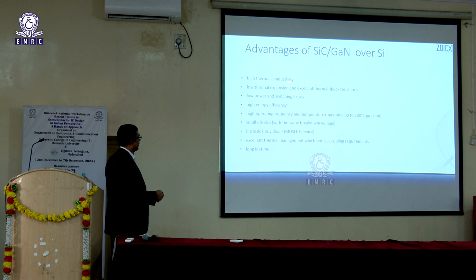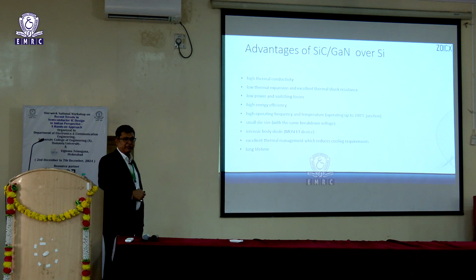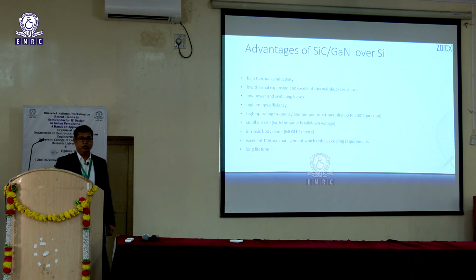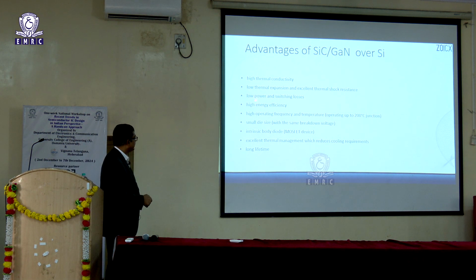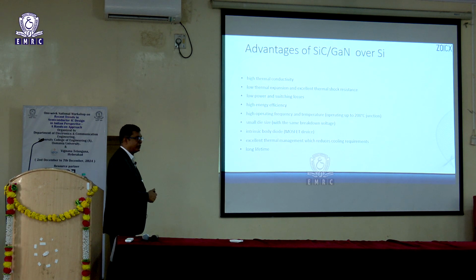I told you about the high thermal conductivity, a very important property for highly reliable systems. Typically for rail traction and space applications, they prefer high thermal conductivity, low thermal expansion, and low power and switching losses because they have a very low RDS(on). Silicon carbide based MOSFETs have low RDS(on) and also a high electron carrier mobility, which reduces the switching losses too. They are highly energy efficient because there is less power loss. They can operate at a high frequency and temperature, as we already discussed.